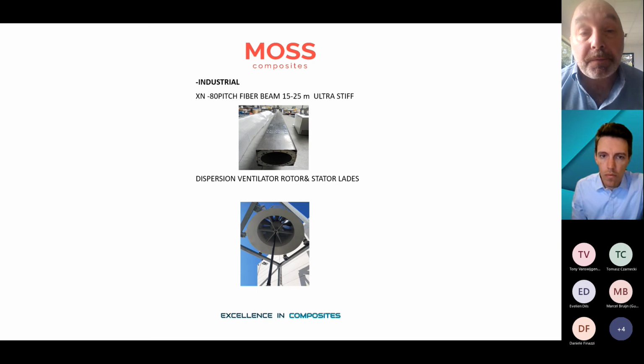This is one, if somebody knows something about carbon fiber, this is a full carbon pitch fiber beam. It's a very stiff carbon fiber. I think it's one of the stiffest probably, the XN-80, and it gives a stiffness of around 400 gigapascal at best. So it's not bad, if you compare this to steel or the normal carbon fiber.